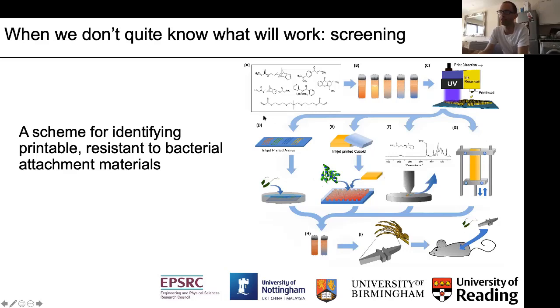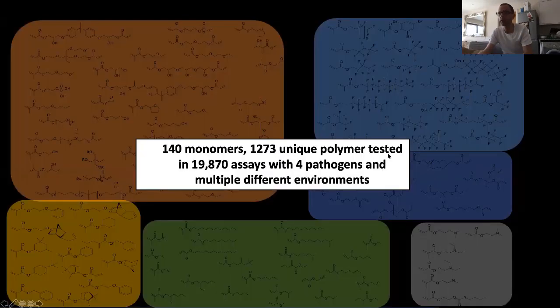And so what we decided to do was buddy up with some colleagues who were creating screens of polymers, typically UV curable polymers, and looking for various different, what we call cell-instructive behaviors, and in this case, resistance to bacterial attachment. So what we decided to do was key into that screen, identify polymers that look like they would be printable, and then scale them up and demonstrate that when you 3D print them, that you could take it all the way to the application stage. In this case, in vivo preclinical studies, and we were able to do that.